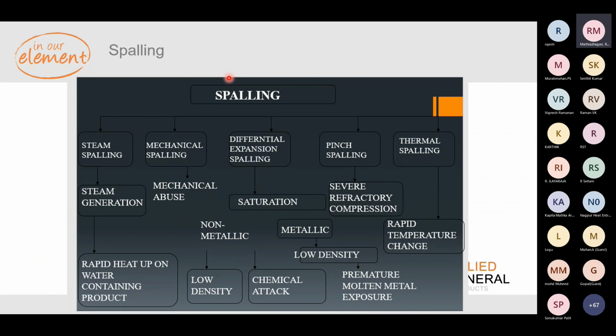So spalling, it's because of spalling. Normally, it's like a piece of refractory falling off from the hot face or in the bottom. It can be either because of steam spalling or mechanical spalling or differential expansion or pinch or thermal. Steam is mainly due to steam generation. It's because of the moisture.